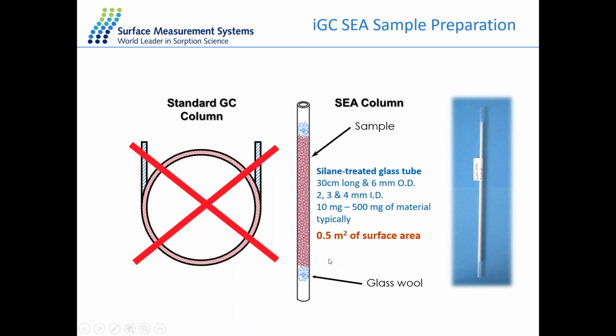Alternatively, if you have quite a large column size, what you can do is insert some silanized glass wool between your sample packing. So this will reduce the pressure, and because it is silanized glass wool, it doesn't interact with any of your experiments. And then we have a nice separation between your sample. Once you do run your experiments, we've done some column to column reproducibility studies, and we haven't seen any difference in the results.